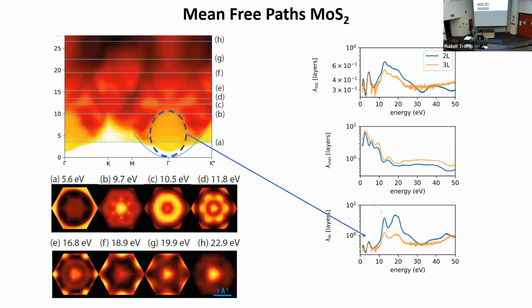What's more, it's very strongly angle dependent. So if you look here at 5.6 eV, you see, there's very strong angular variation. So not only is the mean free path dependent on energy, it's also dependent on momentum, because different momenta have different band structures, different bands in different places.